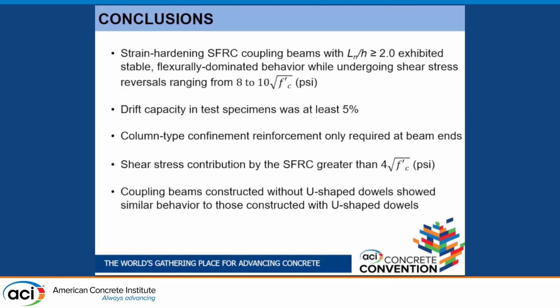So just to conclude, I've shown that if we use a strain hardening fiber reinforced concrete in coupling beams with an aspect ratio of at least 2, we can achieve a stable hysteresis dominated by flexural deformations, even for cases of coupling beams subjected to shear stresses as high as 10 root of F prime C psi.